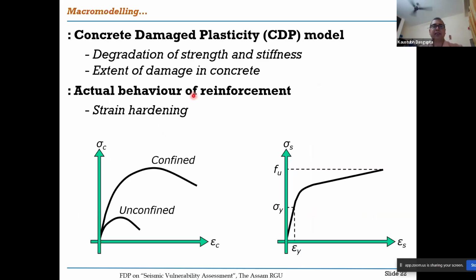So as I mentioned, the concrete damage plasticity model has to be considered for concrete. This takes care of degradation of strength and stiffness. Because when you look at the behavior of concrete, as you can see here, whether it's unconfined or confined, first it picks up strength and then it reaches a peak value, then drops. So this part is the ascending part where it is picking up strength. This part is the degrading part. So the strength degradation reflects or captures the damage. Once it goes in degrading part, that means the damage gets started, right? So whether it's confined or unconfined, the damage will be there.